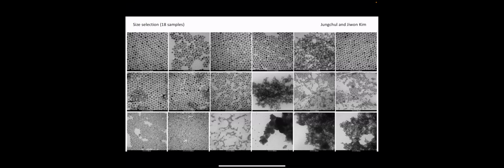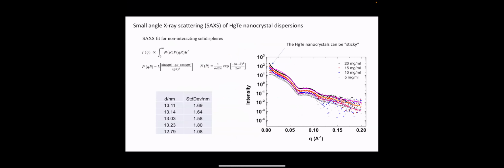So just consider, once you understand that you have to use lower temperatures for the growth and that sort of thing, it's not too challenging to grow decent mercury telluride nanocrystals. So these are spherical nanocrystals after a bunch of size selective precipitations, and these particles were grown with mixtures of oleylamine and trioctylphosphine oxide, and TOP also. But using NMR, we can see that for sure the trioctylphosphine oxide and oleylamine are both bound to the surface of the mercury telluride. So both those ligands are playing a role there.